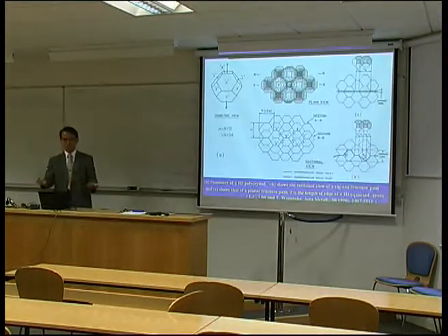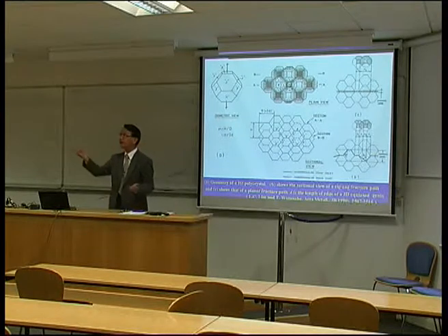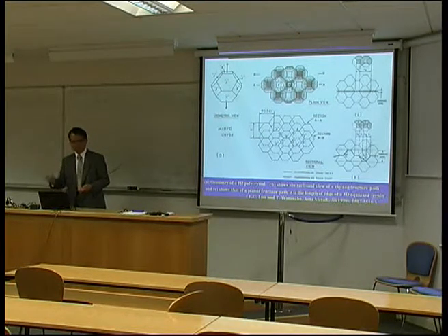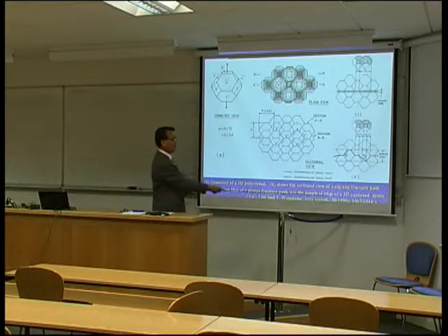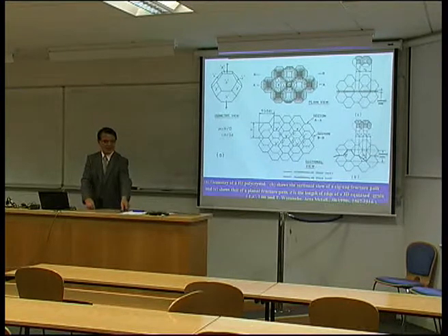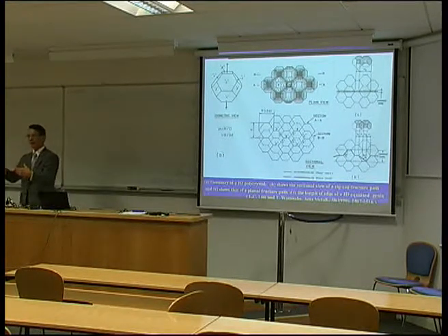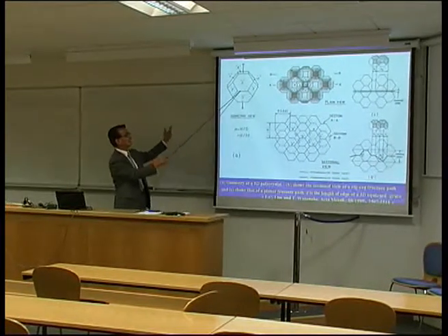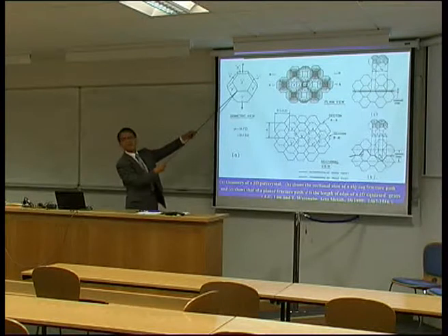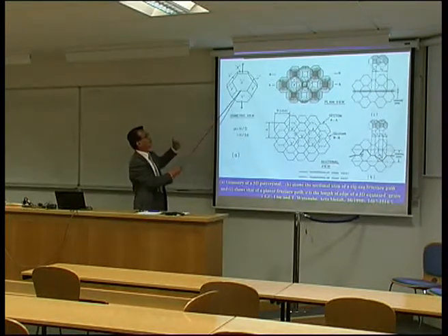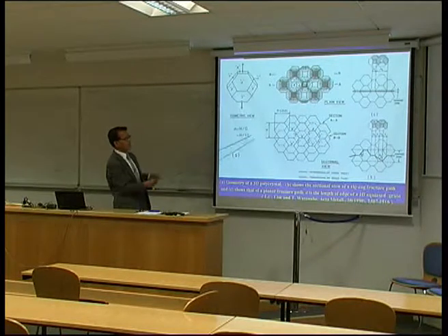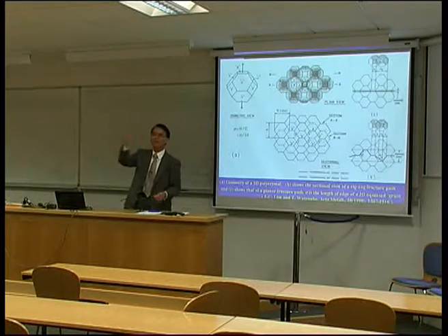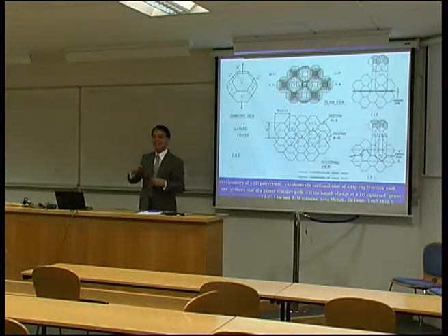Anyway, to control brittleness or intergranular brittleness, how can we design the grain boundary character distribution or boundary connectivity? So sometimes we need to do modeling. About more than 15 years ago, we modeled the fracture process in polycrystalline material using, as you know, tetrakaidecahedron shaped grains. Polycrystalline material consists of a huge number of grains with such a shape. And then we distribute low energy boundaries and high energy boundaries, or in other words, weak boundaries and strong boundaries. And then we see how a crack can propagate in three dimensions.